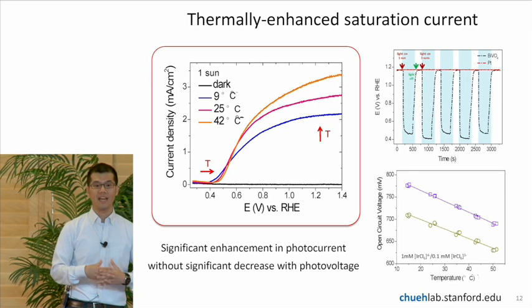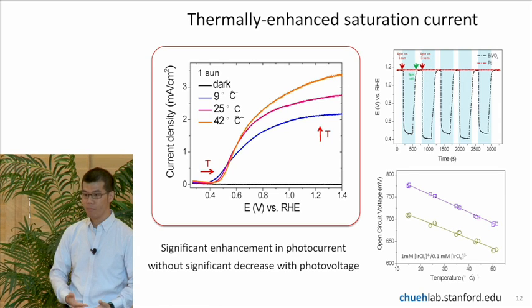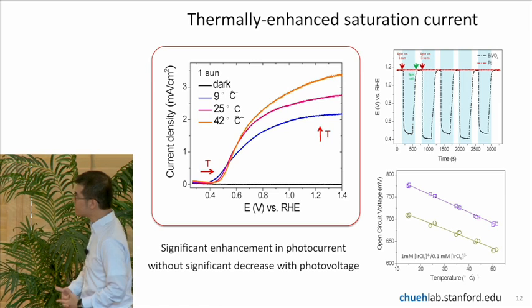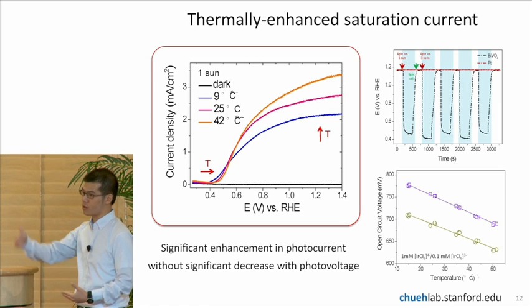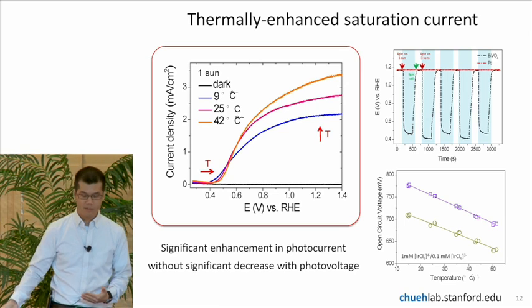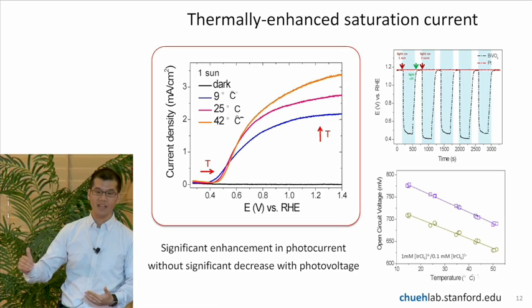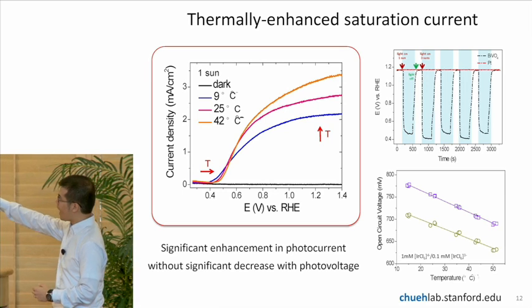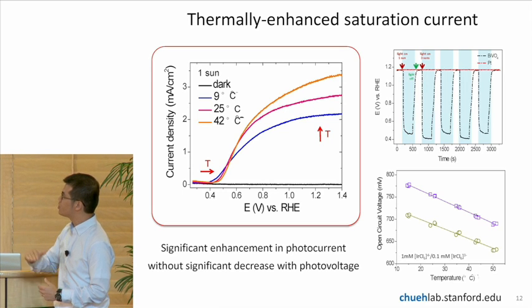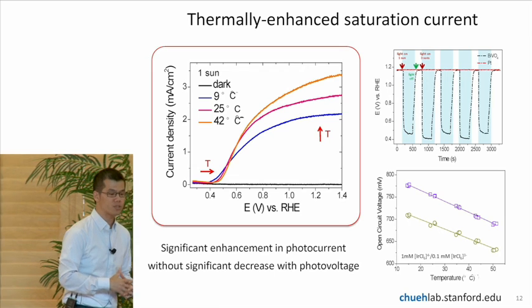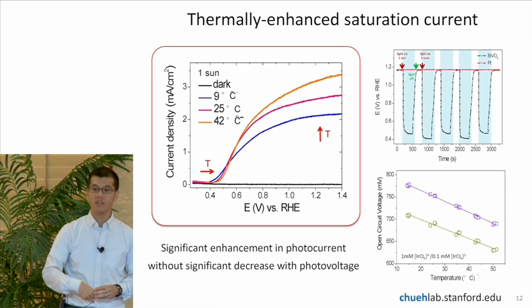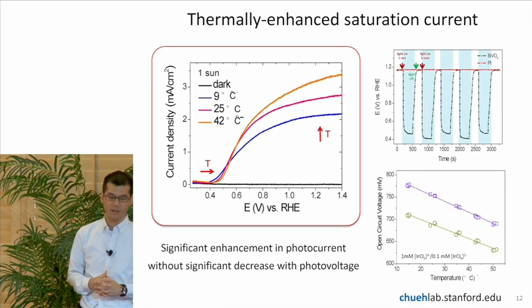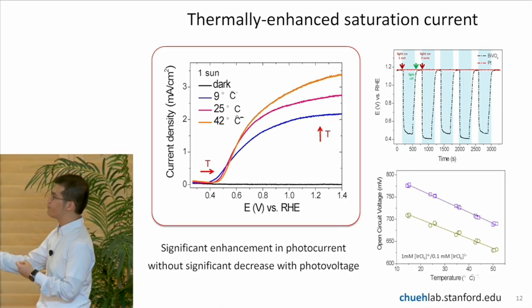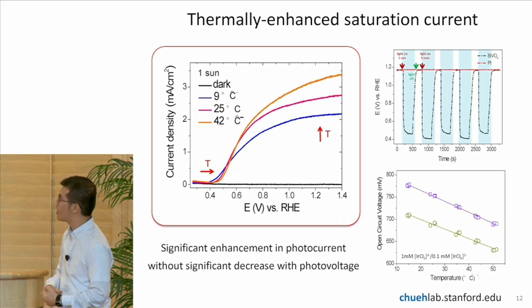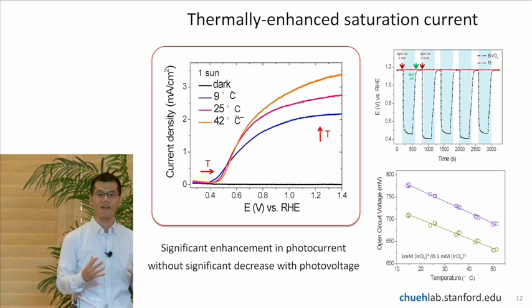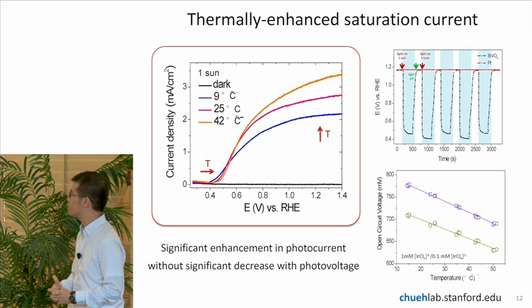Well, we saw actually an even more dramatic dependence on temperature than iron oxide. In the case of bismuth vanadate, when we increase the temperature, the current under illumination versus voltage rises significantly with temperature. If you take a look at the higher voltage part, you can see that the current actually increases by almost 50% as we go from 9 degrees Celsius to just 42 degrees Celsius, just a very small temperature increase. And then simultaneously, the voltage barely changes, the onset voltage on the bottom. So this is great because we're maintaining a very high power output of the photoelectrochemical cell.